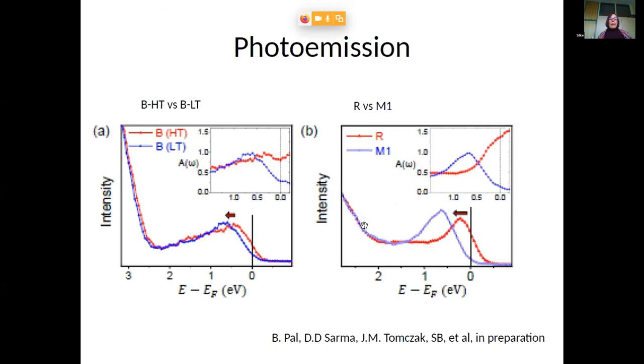Okay, so if we compare the photoemission spectra of the high T and low T B phase to the previous rutile and M1, then we get actually quite similar picture. So here you have the low temperature B phase with a gap at the Fermi level, and in the HT phase you have some spectral weight which looks relatively similar to the scenario that you have in the rutile to monoclinic transition. So this is just a different photoemission experiment from what I showed you before, because this was supposed to be under similar conditions here.